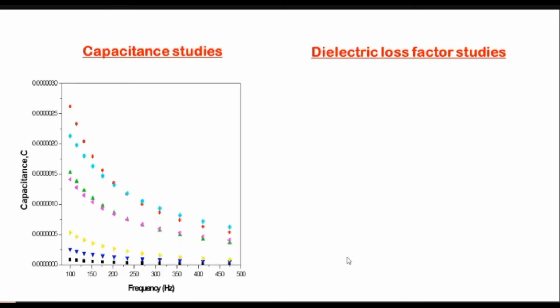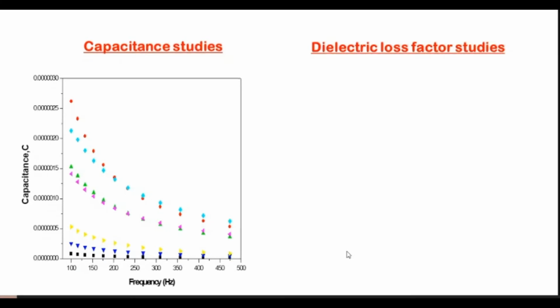The capacitance studies. From the capacitance studies, we know that the capacitance decreases with an increase in frequency. As the frequency increases further, it becomes constant. Here we can see that on co-doping the carbon dots, the capacitance shows a 5-fold increase. Thus, we can say that by preferential or selective doping of these carbon dots, we can enhance their supercapacitance.